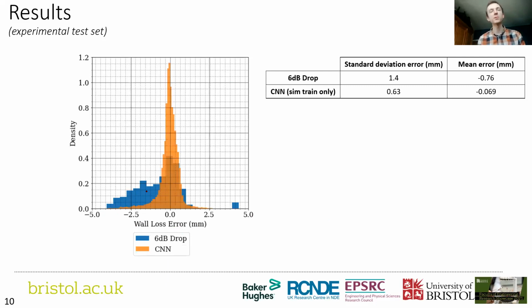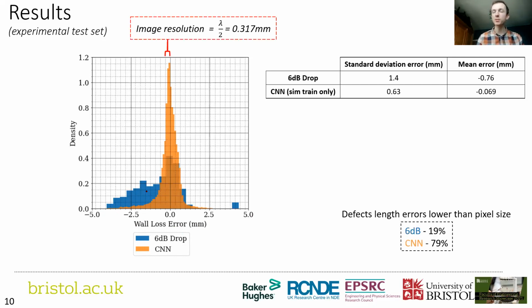Deep learning does far better. Even if I'm training this entirely on simulated data, it does really well on the experimental data with a standard deviation of 0.63 mm. I'm super happy with these results. In fact, 79% of them are lower than a pixel size in error. Those of you familiar with NDE might notice I've got quite coarse images, so the resolution is half a wavelength. I have experimented with making the pixels even smaller, but while the images look prettier, it doesn't actually offer any more information because that's at the diffraction limit of what you can get out for my wavelength.